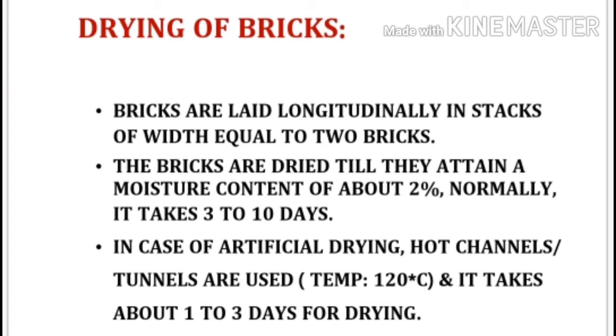Drying of bricks: Bricks are laid longitudinally in stacks of width equal to 2 bricks. The bricks are dried till they attain a moisture content of about 2 percent; normally it takes 3 to 10 days. In case of artificial drying, hot channels or tunnels are used at a temperature of 120 degrees centigrade, and it takes about 1 to 3 days for drying.